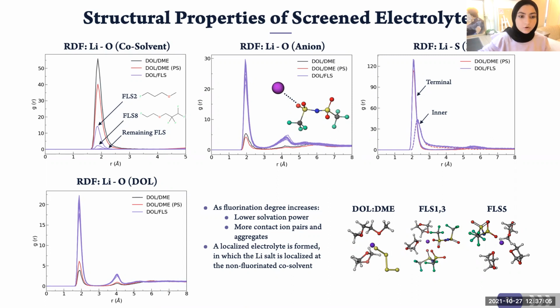On the other hand, for the coordination with DOL, we see an opposite trend, where in the system that has the conventional electrolyte, there is a weak interaction with DOL because most of the interaction is happening through DME. And in the fluorinated solvents, most of the solvation of the cation is coming from the DOL solvent. So for the fluorinated electrolyte, we can conclude that the DME solvent that is conventionally present in the electrolyte gets replaced with DOL for solvating the cation.